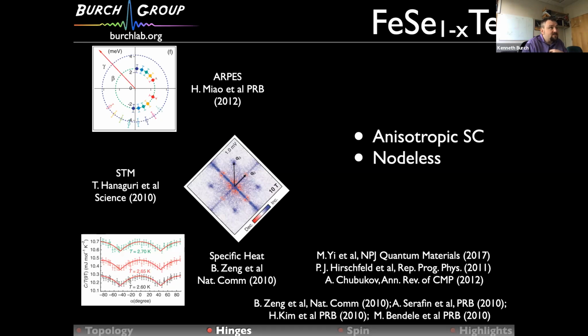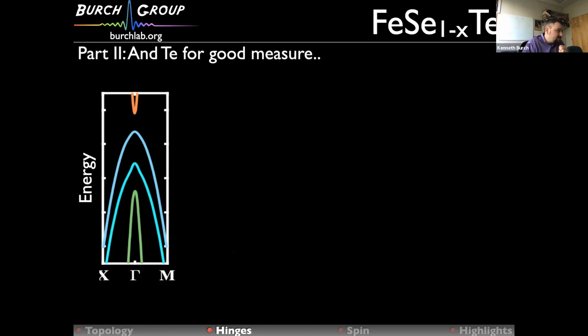So you have this potential S plus minus superconductor, and it turned out the chalcogenide system is particularly interesting because of its large spin orbit coupling. And so about 5 years after the discovery of the iron-based superconductors, there was this very interesting proposal that came from two theoretical groups that noted the following.